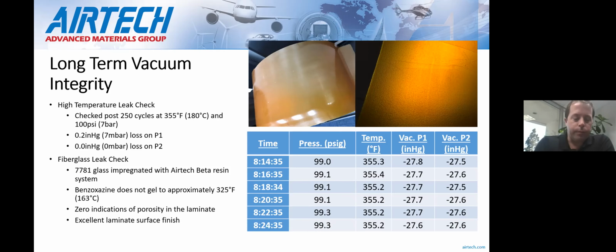For those of you not familiar with the process, you take some thin fiberglass, like a 7781 style fiberglass, and we impregnated it with our own benzoxazine resin system. Typically in the industry, they're done with epoxy, but we chose our benzoxazine specifically because of the very high gel point of 163 C, where the benzoxazine starts to cross-link and thicken.